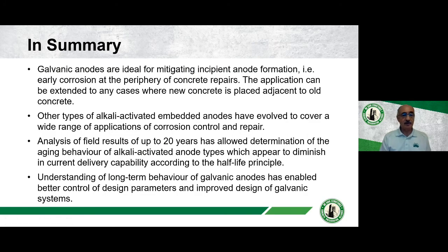Okay, so I'll summarize all of that. What I said basically is that galvanic anodes are ideal for mitigating incipient anode formation, and I've given examples of that. That's in patch repairs or anywhere where you have new concrete cast against old concrete, and steel reinforcement needs protection, or it needs to be able to prevent corrosion from occurring. There's also other anodes that have been developed, also alkali-activated embedded anodes that can cover a range of applications in what we call corrosion control, and that it could be a grid formation of anodes that protects a certain area of your reinforced concrete.